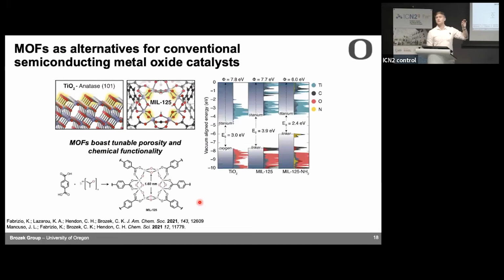So as a first taste of what we could do, I wanted to study this other famous MOF called MIL-125. MIL-125 is a porous molecular version of titanium dioxide. MIL-125 contains these octameric titanium oxo clusters. Unlike TiO2, which has a band gap that's fixed at 3 eV, one of the reasons people really like MIL-125 is because you slightly change the environment around the titanium metal ions, and you change that band gap a lot. In conventional MIL-125, the band gap is around 4 eV. If you put an amino group next to the titanium, then you decrease it by about 1.5 eV.